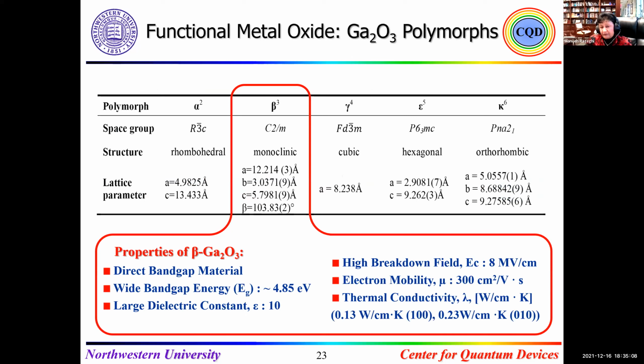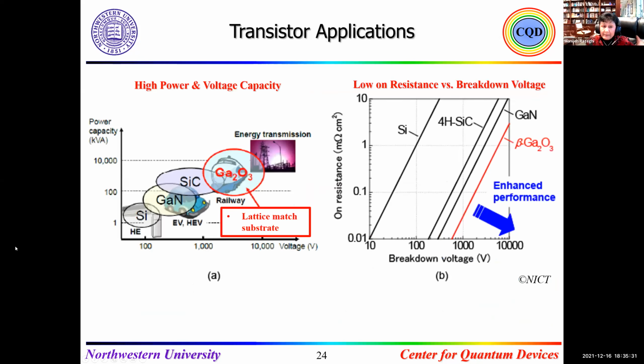At the present time, there are many different groups working on this in Germany, Japan, United States, Notre Dame, and at the same time in France. They have 2-inch substrate lattice matched for beta gallium oxide. It has already been demonstrated that high power and high voltage capacity gallium oxide can give much higher breakdown voltage compared to silicon carbide, gallium nitride, or silicon, along with lattice matched substrates.